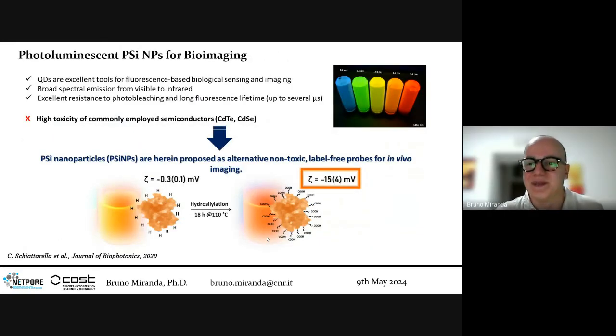Very fast, as I told before, we have photoluminescent nanoparticles obtained from photoluminescent porous silicon. We mechanically detach the membrane and ultrasonicate it in order to break it into nanoparticles. The advantage of using porous silicon nanoparticles as labels in bioimaging is that they are non-toxic.